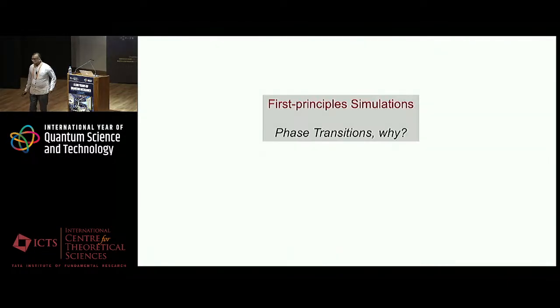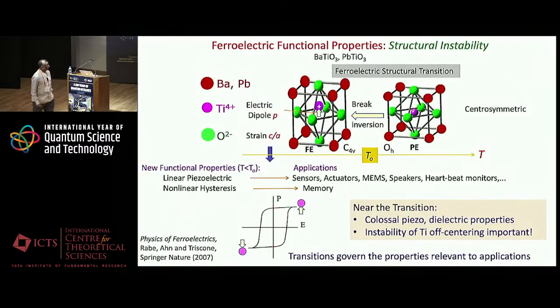So the first point I'll make is phase transitions, in particular structural phase transitions in crystals, and how we can simulate them using first principles simulations. A simple example I can offer is a ferroelectric material, which is a very important technological material, which takes a cubic structure at high temperature, and as you cool it down, it breaks inversion symmetry to form a tetragonal structure, which is accompanied by a dipole moment associated with the positive titanium atom off-centering along the z-axis, so an ionic dipole moment.